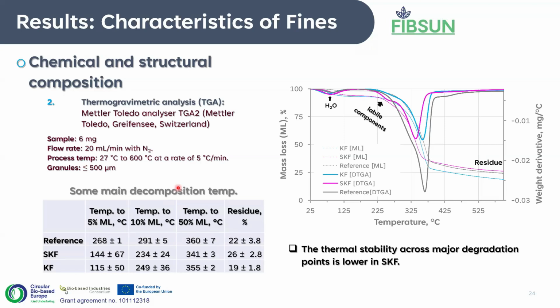Obviously, what we see with the reference is lower cellulose content. However, we see that, for instance, at the 50% mass loss, which is often associated with about 50% of the material incorporating cellulose thermally degraded, this wood reference actually has better thermal stability compared to the hemp biomass. So you could ask why that is. If cellulose has this kind of high thermal degradation, but we noticed as well that wood had quite a substantial amount of lignin, which often has a high variation in thermal decomposition.